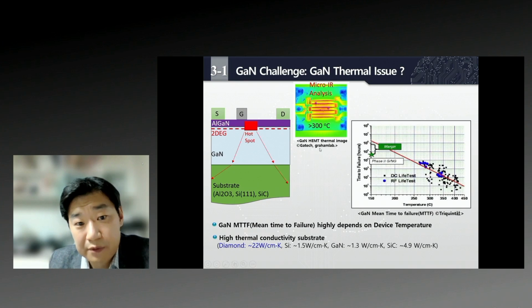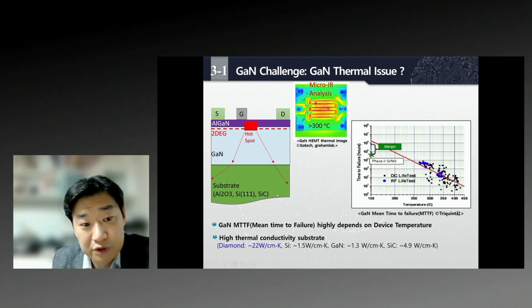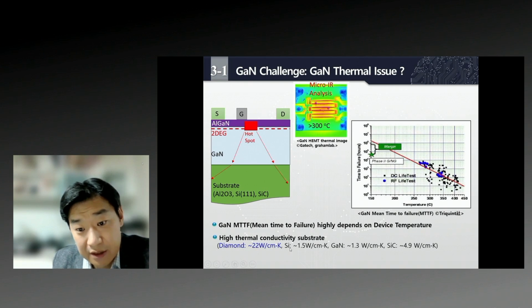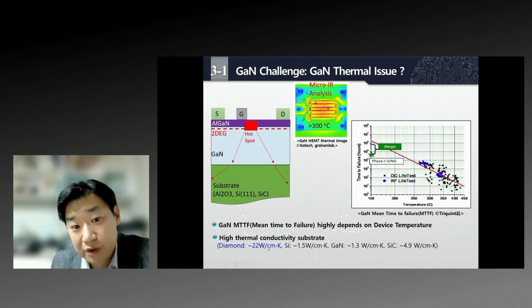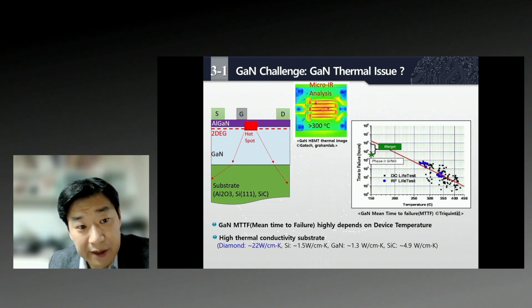To solve these problems, we typically use silicon carbide, a substrate with better thermal conductivity. Some groups use a more aggressive approach with a diamond substrate. It has 5 times higher thermal conductivity compared to silicon carbide.